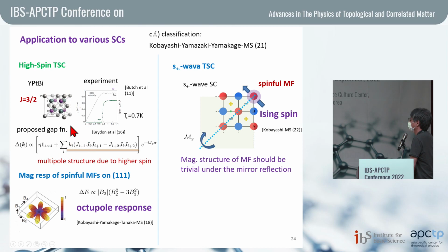And to explain these nodal structures, they proposed parity mixed superconducting states. Actually, this material doesn't have inversion symmetry. So this is a non-centrosymmetric superconductor. So it allows a parity mixed superconducting state. Importantly, because of the higher spin structures, the superconducting gap has a multipole structure due to higher spin. Correspondingly, we can expect this kind of higher spin magnetic response of the spin-full Majorana fermions. Actually, we found that if you consider the (111) surface, we can obtain octupole responses. So this is very consistent with our theoretical argument.